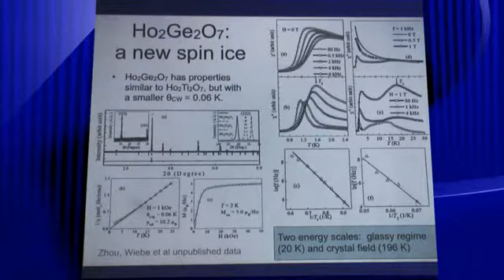Now, before we go on to dysprosium, I mentioned some of the properties of the holmium germanate. We have a paper that we're preparing for Physical Review Letters. This is just showing you that across the series, if you go from tin to titanium to germanium, you have a systematic change of your lattice constant. So you go to higher 2 theta, which means going to lower and lower a. The Curie-Weiss constant is roughly 0.06, right? So slightly ferromagnetic, but there's also a dipolar contribution to that.